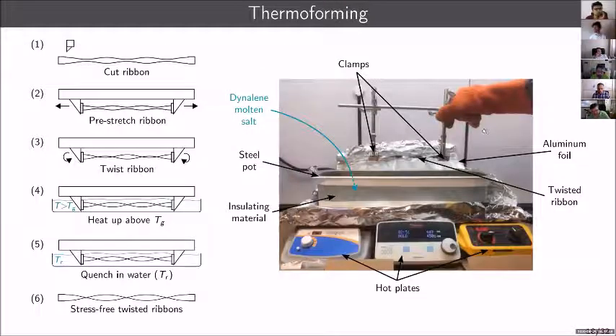Okay, so let's move to the thermoforming. So now what we did was to take a ribbon with those parameters that we selected, we cut it, we pre-stretch it with a custom apparatus, we twist it, and then we heat it up above its glass transition temperature. This is done by immersing it in a molten salt bath. And then we quench it in water. And what we will obtain in the end is a stress-free twisted ribbon.